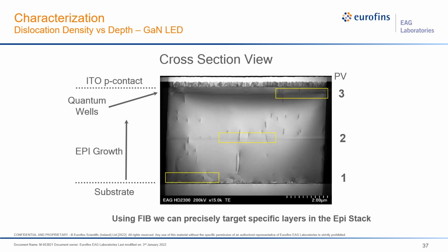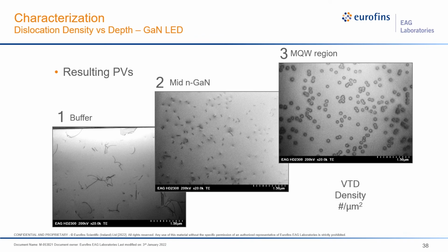So using the FIB, we can target very specific depths in the sample to create plan views. Here, this number 1 is near the interface with the substrate, so the buffer region. Number 2 is then at the mid growth of the GaN, and then number 3 is just in the active layers themselves. And so we can create different plan views at these different depths to then understand the evolution of the defects in terms of defect density going up through the sample.